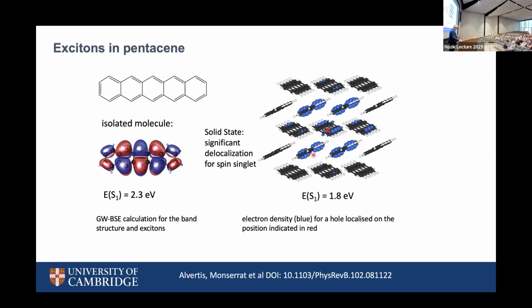When it crystallizes, it's possible to calculate what the wave functions look like. So we have a hole on the middle molecule, and here is where the electron lies. It's not just on one molecule, it's spread over the nearest neighbor and a bit to the next nearest neighbors. We call it an exciton, an excited molecular state, but it's much, much tighter, much more confined than you would see in an inorganic. And that's just down to the low dielectric constant.